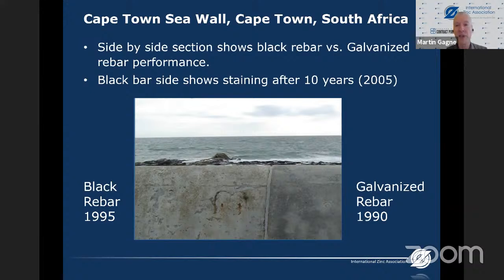We can see this photo was taken in 2005, after 10 years, and there's some red rust staining. We can see some cracking of the concrete coming through on the black rebar side, but not on the galvanized rebar side. So again, in a direct comparison, in the exact same environment, the galvanized rebar, even though it's older, is outperforming the newer structure constructed with black rebar.